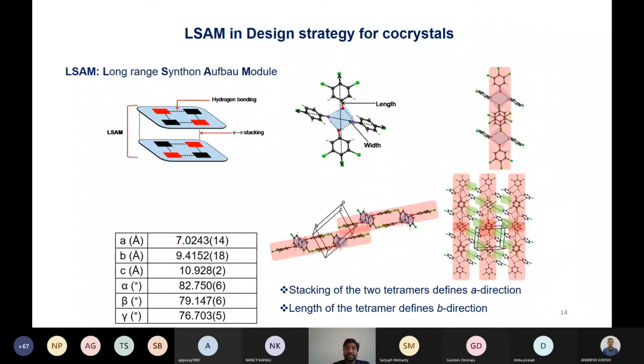bonding and pi-pi stacking. As I said, it is sometimes easy to find LSAM in a crystal structure, but it's very difficult to design, because what you have to avoid here is synthon competition. For that, you have to take two synthons which are not so comparable in energy, and also which are in different directions. So hydrogen bonding and this pi-pi stacking, we got this idea from the modularity concept, that we observe